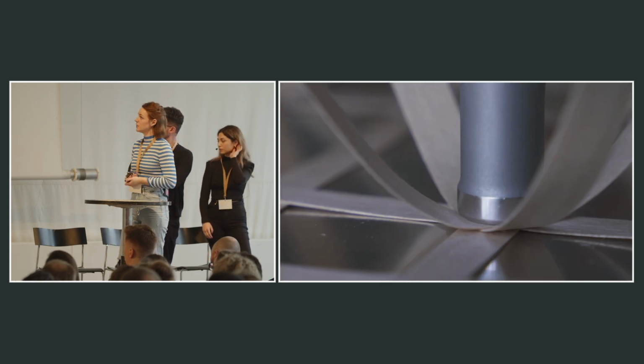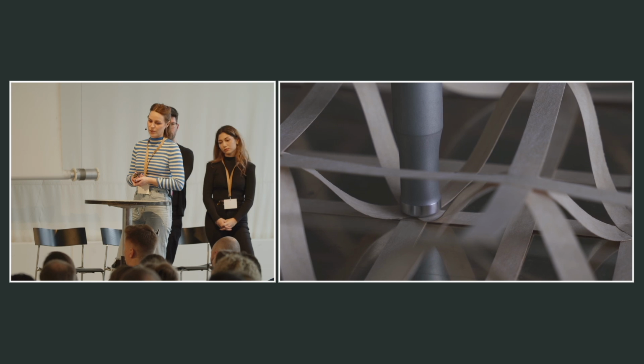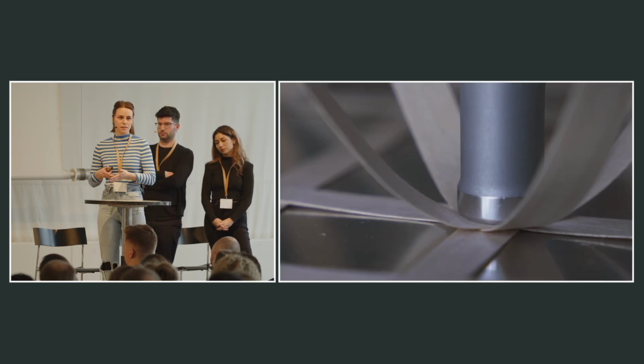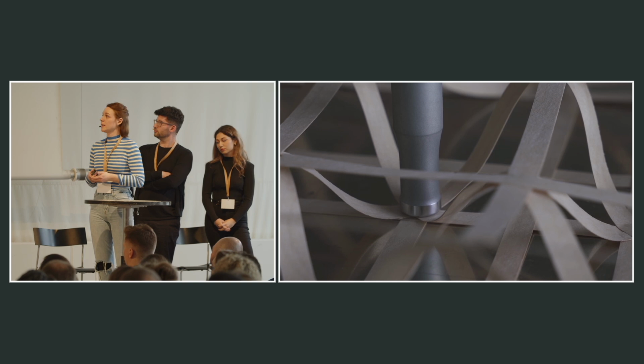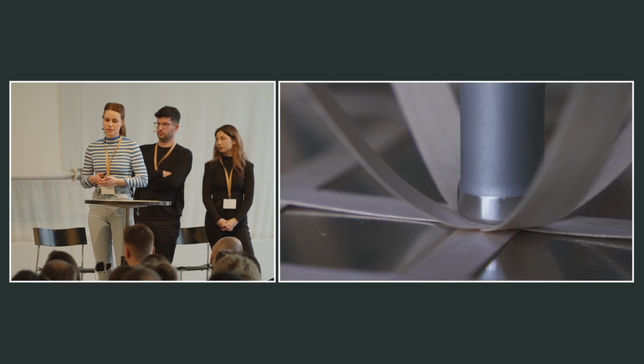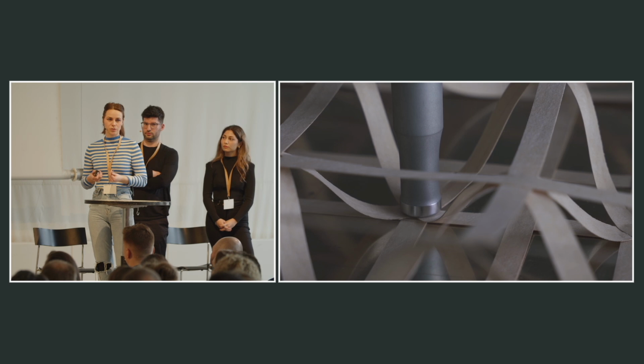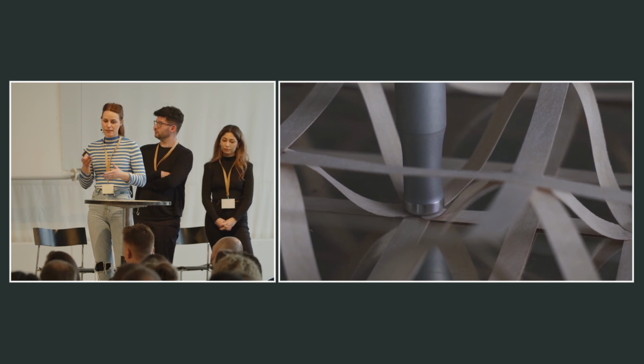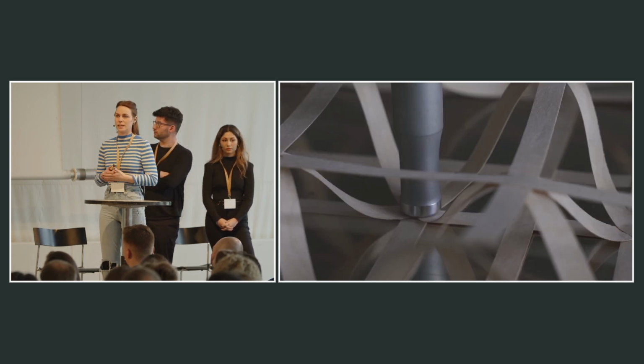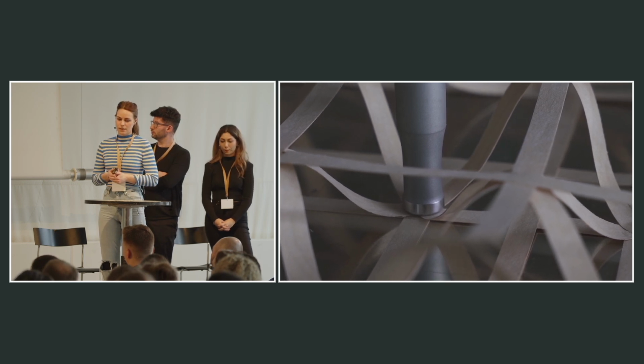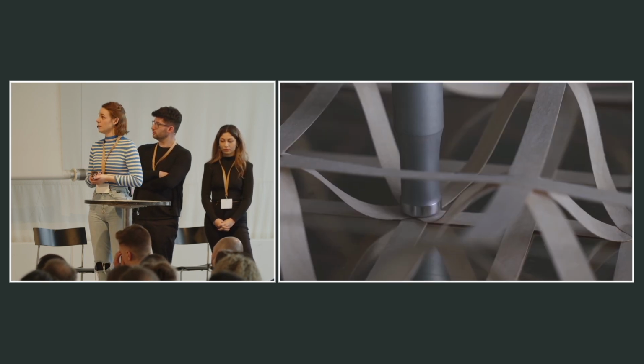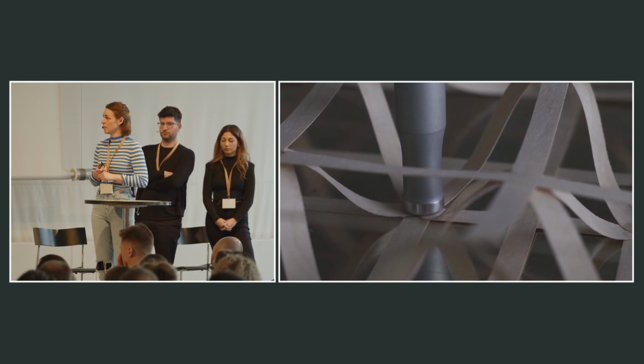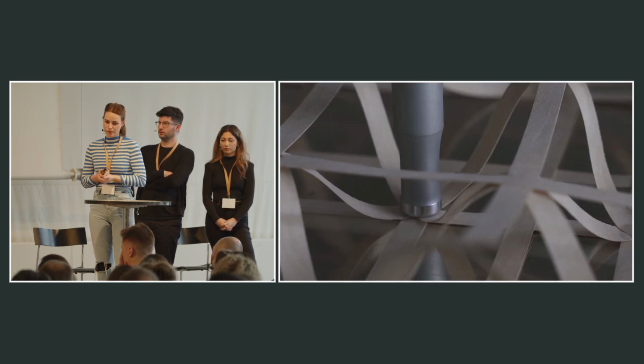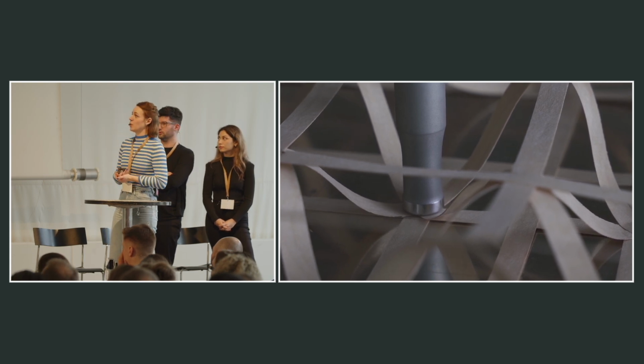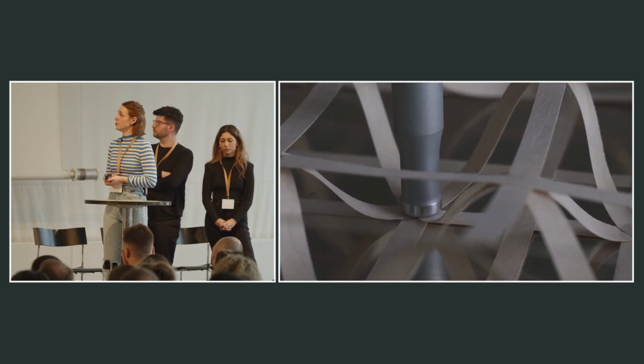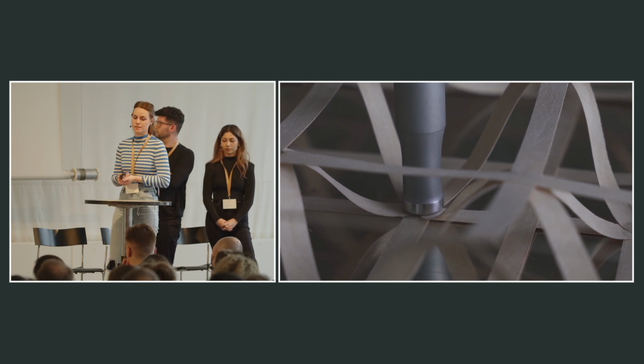The ultrasonic welding uses a titanium horn that vibrates at high frequencies while being pressed on the material. And the kinetic energy is then transformed into thermal energy, which melts the lignin which occurs naturally in the wood veneer and binds the strips together in a fraction of a second. And we did some tensile testing and demonstrated that these bonds are actually stronger than the veneer itself. And so we proved that this is a suitable method for the production of the veneer lattices.